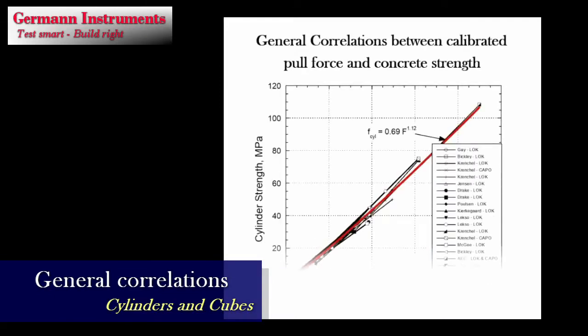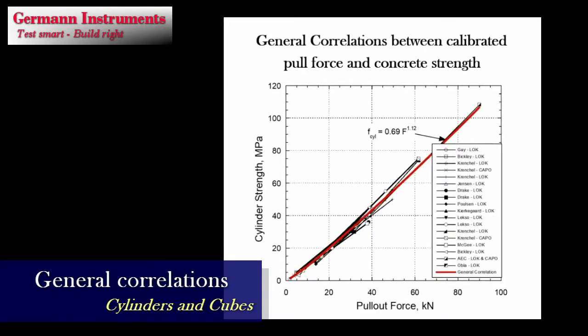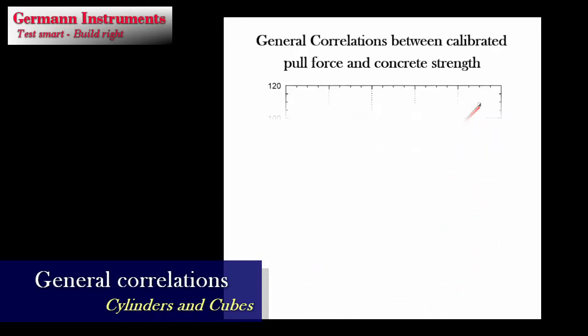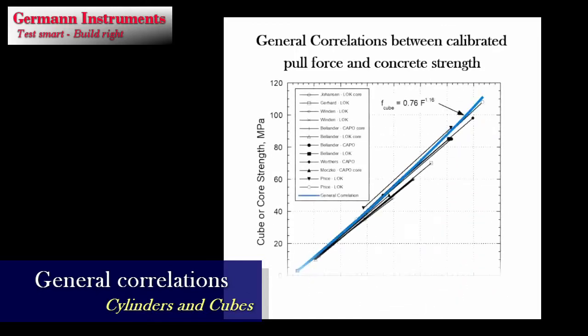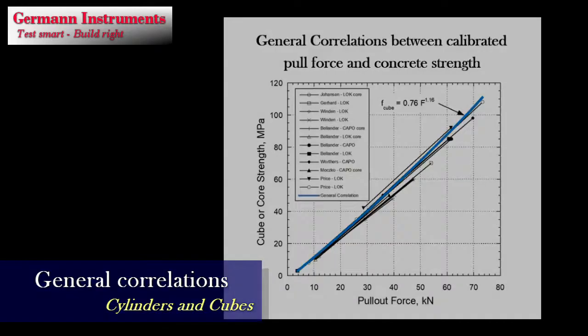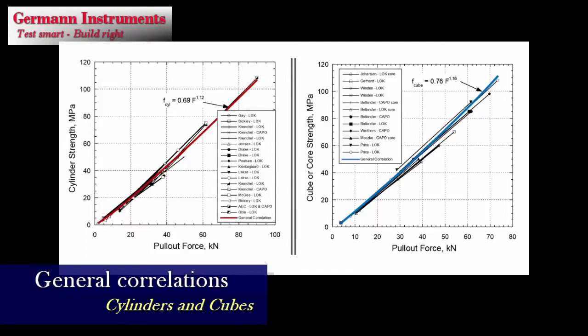The property measured, the pull-out force, is related directly to compressive strength. That is why robust, general correlations exist between CAPO-Test pull-out force and standard cylinder, cube or core strength, verified during the past 40 years in many correlation programs worldwide. All concrete parameters have been investigated, such as different cementitious materials, water-cement ratio, age, air entrainment, curing, admixtures, depth of carbonation and type, shape and size of aggregates up to 40 mm. The use of lightweight aggregates, however, produces a significantly different correlation.